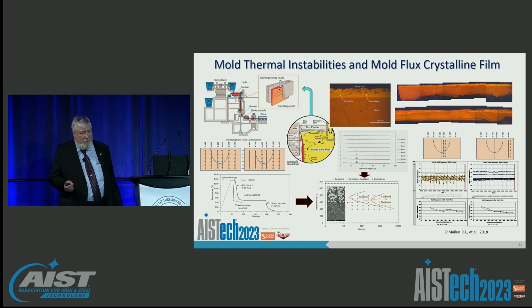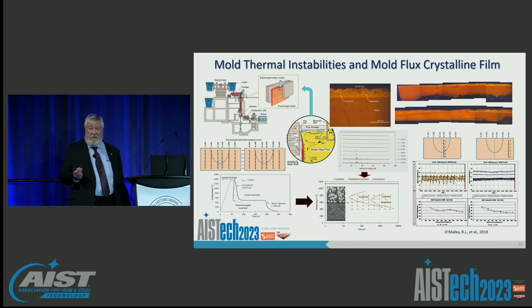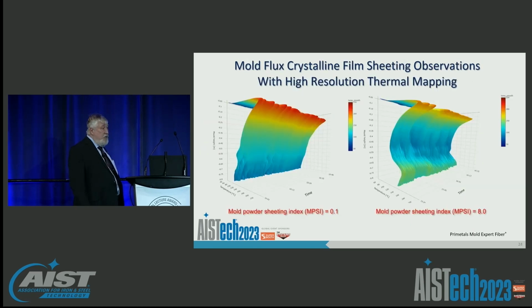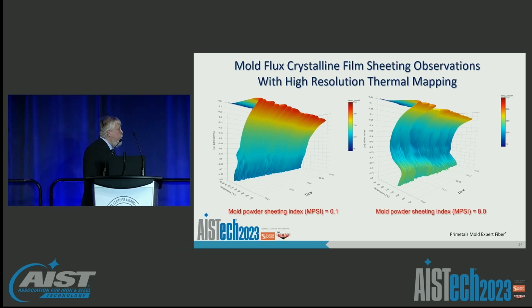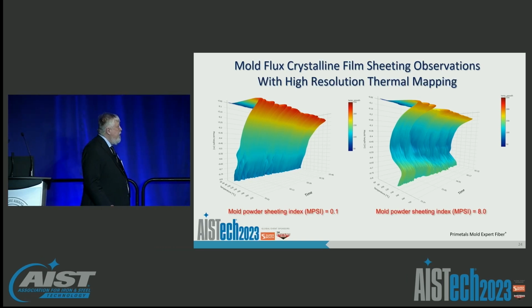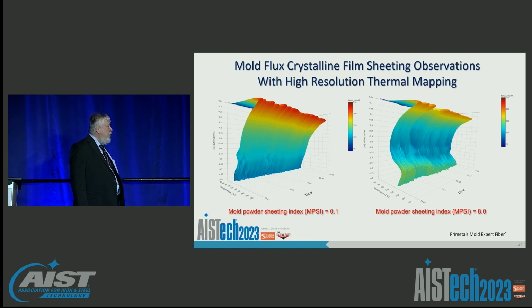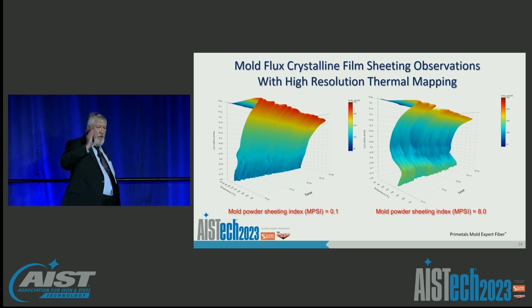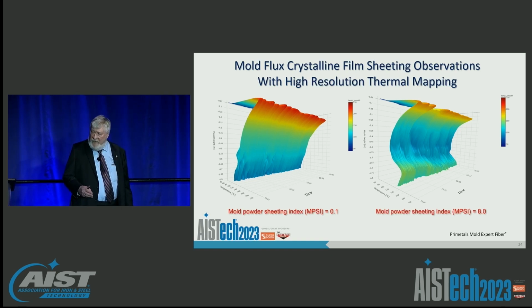And the key to solving that problem is developing these flux films so that they remain stable under the stresses of the withdrawal environment of the casting process. With these new fiber optic systems, we can see these behaviors directly. And you can see here on the left versus the right, different fluxes in different steel environments that show essentially jumping behavior as a function of time lower in the mold that is directly related to this film sheeting behavior. If that sheeting behavior travels too far up close to the meniscus, we have catastrophic events take place.